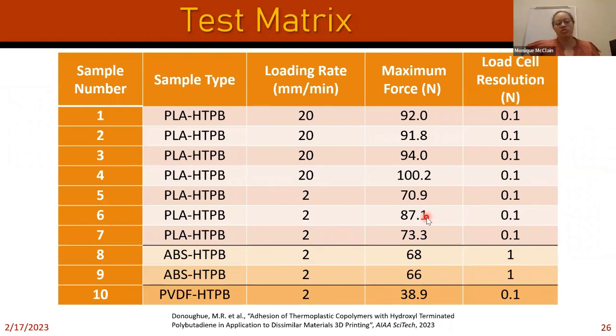So here I have that test matrix, and there are many more tests to go. We did change the thermoplastic material type. We also changed a few things like loading rate just to get our bearings on how this test was working. And then I have the load cell for reference. In general, there is clearly a loading rate dependence, which is not unexpected.